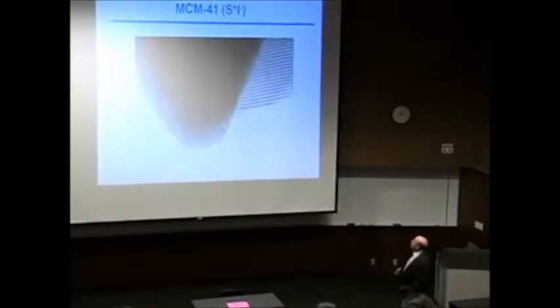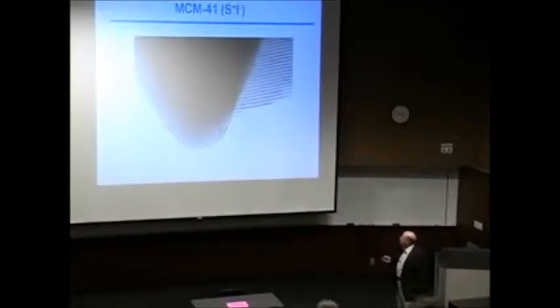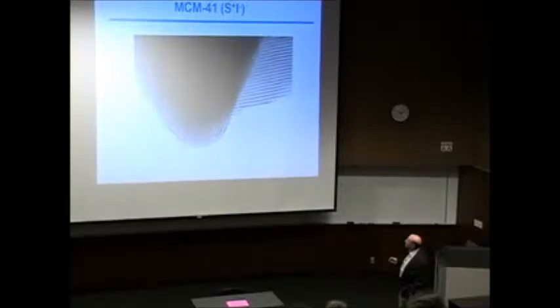So you get this beautiful long-range order that is really the consequence of what we call electrostatic assembly. In other words, a better way of saying it is that if this is a surfactant micelle in this pore, it is interacting with adjacent surfactant micelles in adjacent pores through electrostatic interactions. In other words, the forces directing the structure are just like the forces directing the structure of sodium chloride. It's the same long-range ionic forces that are operating here.